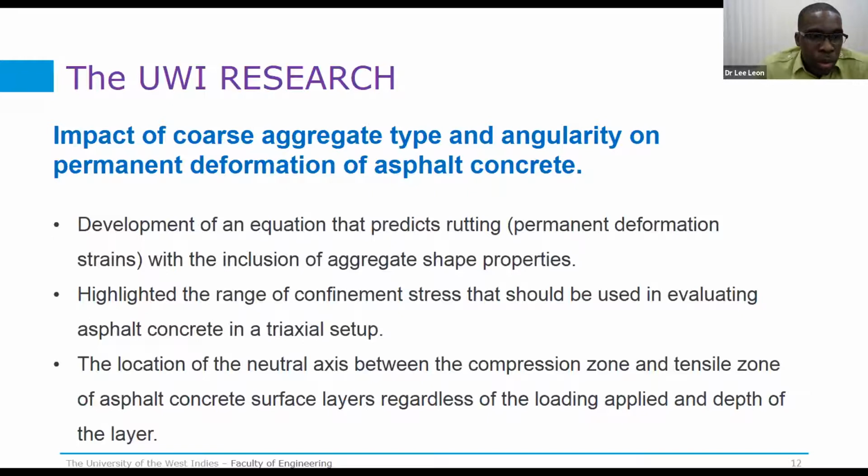We have also highlighted the ranges of confinement stresses that should be used in evaluating asphalt concrete in a triaxial setup, because there are varying values when you look at literature or at different countries of what confinement stress should be used in evaluating asphalt concrete.